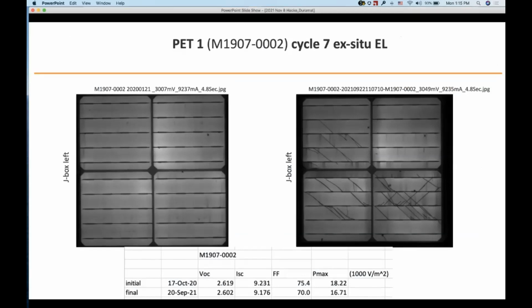Here's the initial and the final. And if there's wear and tear as we stress test the modules, thermal cycling, mechanical loading going on, cracks do develop. And the main thing that falls here, we find, is the fill factor. But there's no major disconnects. There's no major, you know, even electroluminescence, which is highly contrasting of areas that fall off due to open circuits, we really don't see too much.